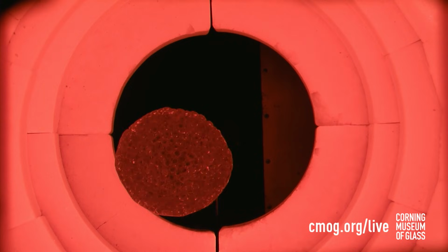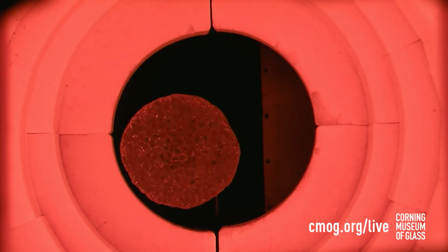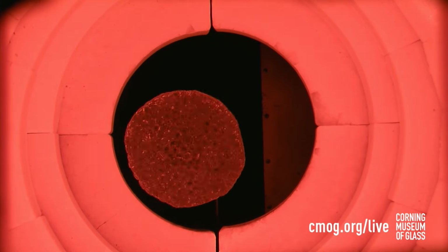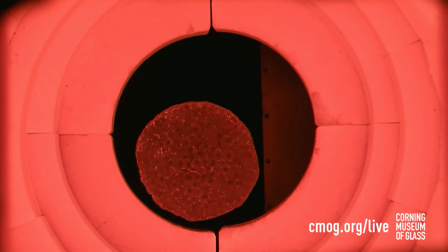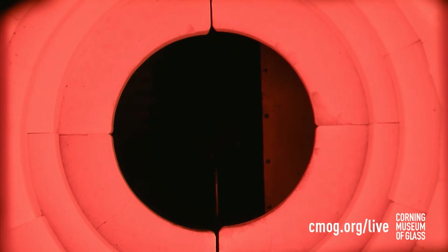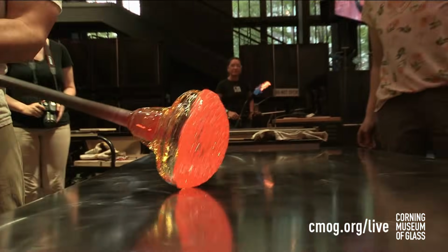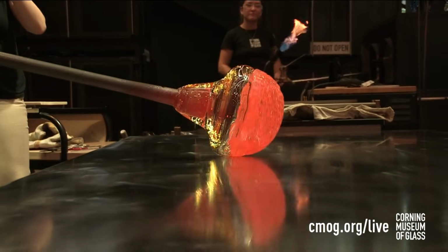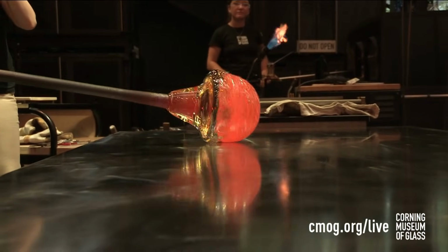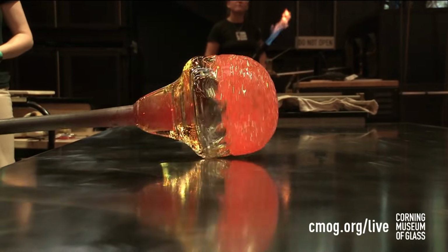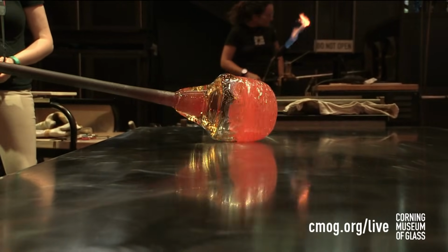If we took that out or you cooked that part of it out, the glass would become so viscous that even at 2,100 degrees, it would be very hard to collect, really hard to work with. It changed the entire way the material worked, basically. So by remelting those nuggets, no, we're not messing up any of the glass. It is designed chemically to be melted twice.